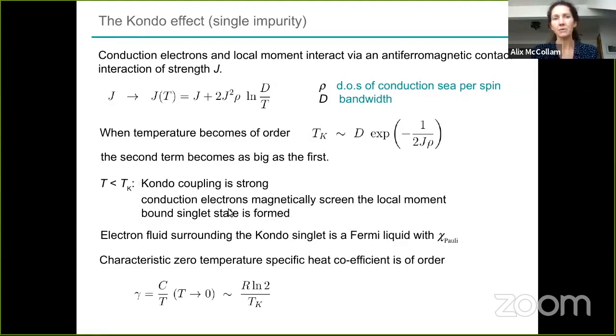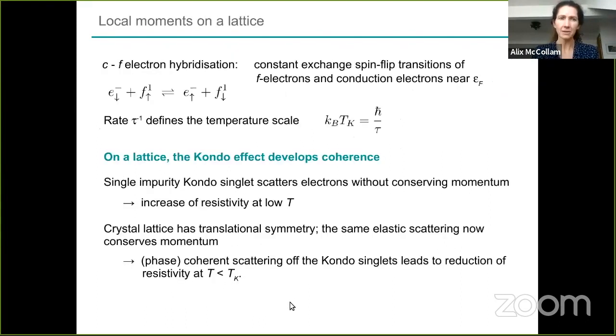So in this case, at low temperature, below the Kondo temperature, which is a characteristic of the material, there you typically have your Fermi liquid with the Pauli susceptibility, as I mentioned before. This is for the case of a single impurity. And when you put the local moments on a lattice, then you get a slightly different behavior because coherence develops. In this case of the impurity here, you have a gamma coefficient that becomes constant and is determined by this Kondo temperature.